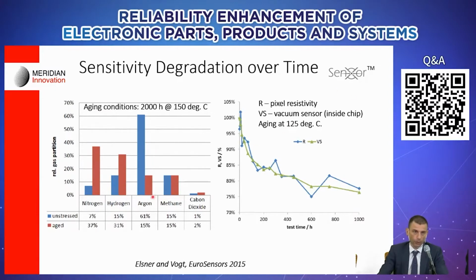Is it possible to accelerate this type of aging effect, let's call it, so that as we ship the product, it's already at a stable sensitivity and we don't see accuracy degradation over time? And here on the left, it's just showing the different gas molecules and their concentration, how it changes as a result of a 2,000 hour stress at 150 degrees.